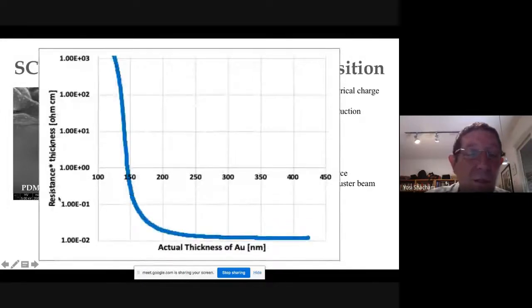And here, Professor Milani is measuring resistance as a function of the actual thickness of the gold. You can see that initially, the resistance is very, very high. This is ohm centimeter. This is very, very high. When the gold film is approximately 100 nanometers, if you have less than this, the resistivity is huge. It's almost not infinite, but gigaohm and more.